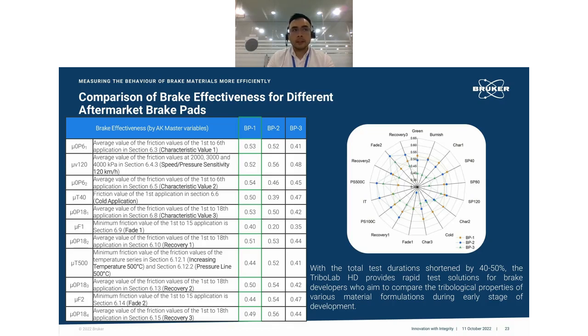These are the brake pads that are already on the road being widely used. So the coefficient of friction values are in the optimum range, a good range across all the different variables tested in the AK Master test. So BP1, the previous results I showed in the previous slides, are all from brake pad number one. We have compared with brake pad two and brake pad three of different makers. But in general, what we can say from this comparison test is that the total test duration is shortened by 40 or 50% using a small scale test compared to a large scale test to understand the frictional properties of brake pads and brake discs.